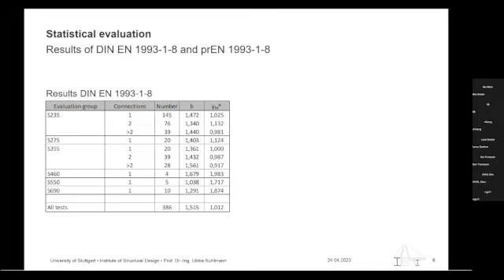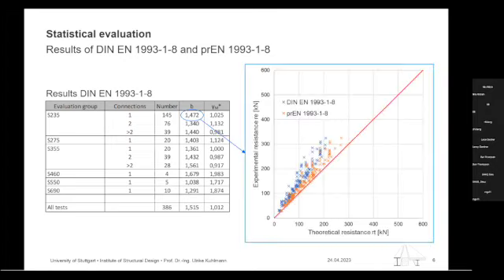I don't want to show you all of my results, but here's an example. You can see the comparison between the experimental resistance and the theoretical resistance of the steel grade S235, and the value correction factor b is very large, which means that the theoretically determined values are significantly smaller than the experimental values, and this is seen on the blue crosses. It can also be seen that there are differences between the design concepts, caused by the different locations of the crosses.